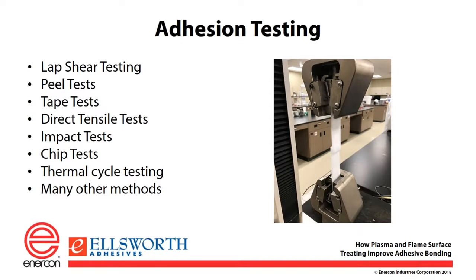Impact tests involve dropping weights onto your part. A lot of times it's big steel balls. In the coatings industry, they use impact testers. And the testing can be done directly, where you directly impact the top surface where the adhesive or coating might be. An indirect test would be where you hit the piece from the back side instead. Then you look to see whether or not you lose adhesion.